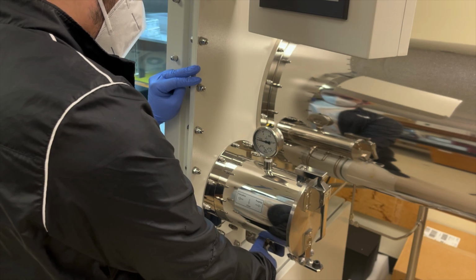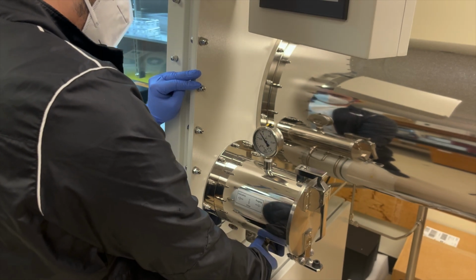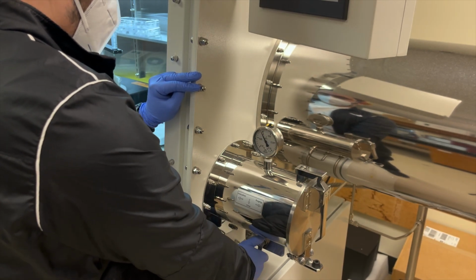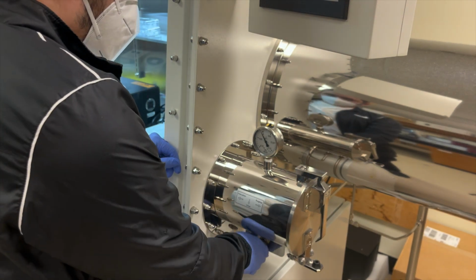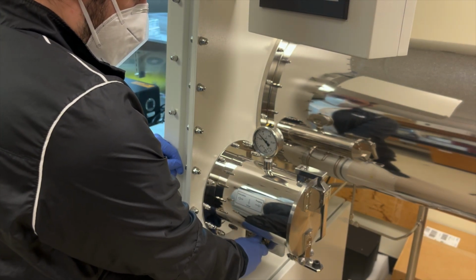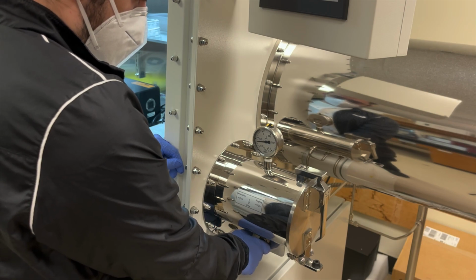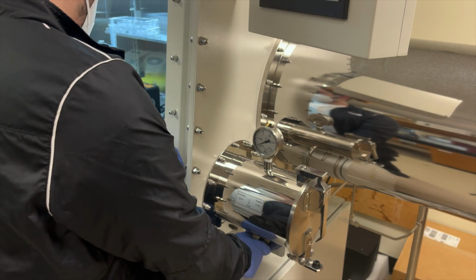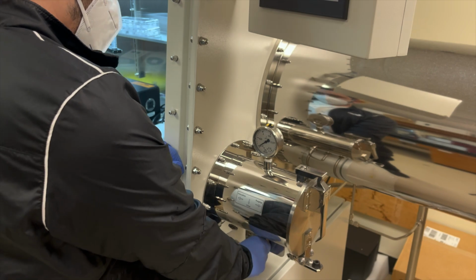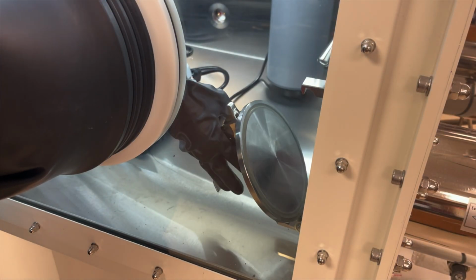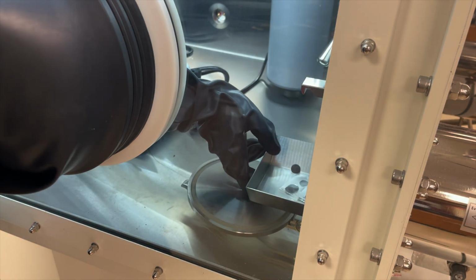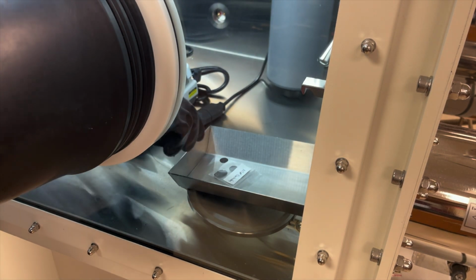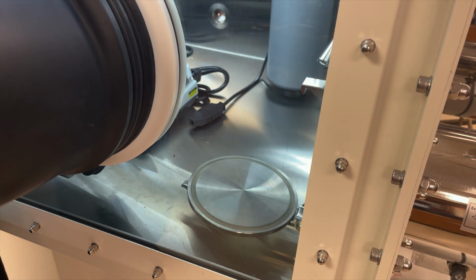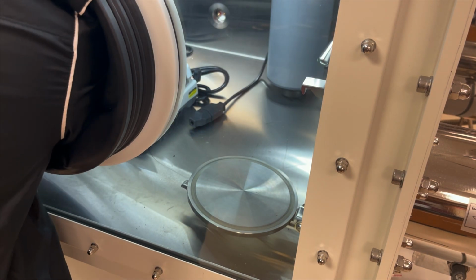Placing the electrodes inside the tray and locking the chamber, we will then evacuate and purge another 3 times. When purging with materials inside of the chamber, be sure to do so slowly, otherwise the electrodes will fly about inside the chamber and may cause damage to them. The assembly of these devices in the inert glove box is unique to our batteries. Note that supercapacitors may be assembled in the open air.